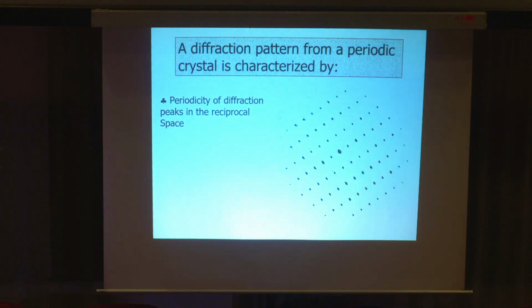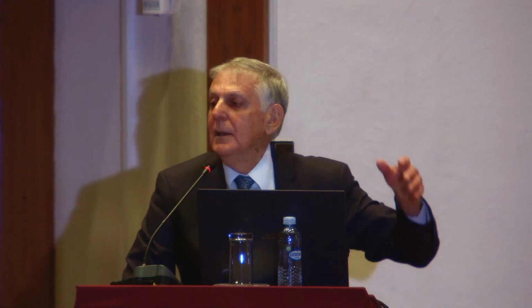The spot in the center is the transmitted beam, and all the rest of the spots are diffracted beams from a crystal which is periodic in the electron microscope. And what you have here is periodicity in this direction, and in this direction, and in this direction, every direction. The real space is similar to the reciprocal space, and both are periodic. Rotation symmetries that are allowed also in the reciprocal space: 1, 2, 3, 4, and 6. No 5-fold rotation symmetry, and nothing beyond 6-fold is allowed in the real space and in the reciprocal space.